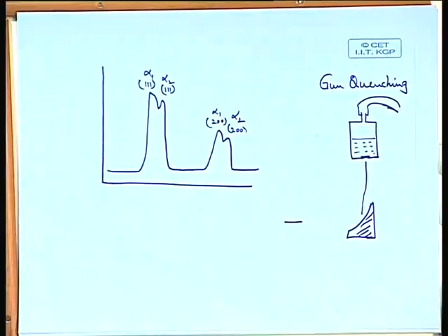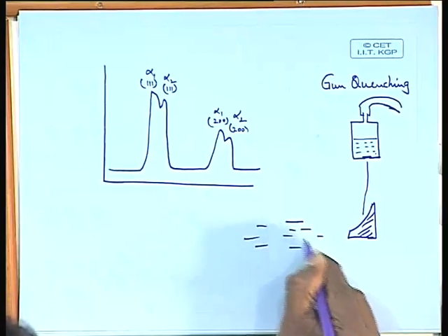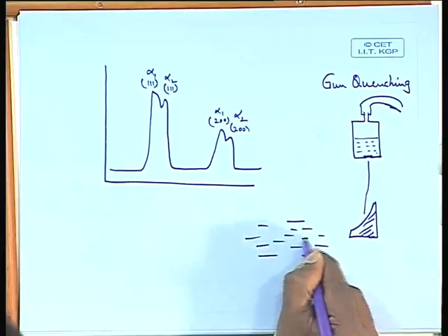So it falls at a very high velocity, and whenever a liquid droplet falls onto the block, it becomes a thin flake. You will have a large number of such flakes falling here. You will never get a continuous ribbon here. A large number of flakes just fall on the floor, and you collect these flakes and do an X-ray of them.